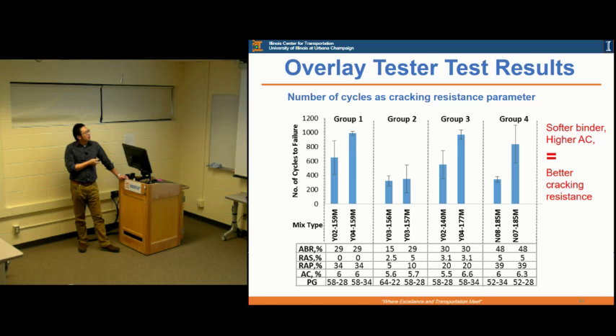Okay, so this is the overlay test results. What you can see, even though the overlay test has very high variation for some mixes, for example 159, you can see these two - you get a softer binder, then you still get higher cycles to failure, which means that if you are using a little bit softer binder, you end up with a higher or better cracking resistance.